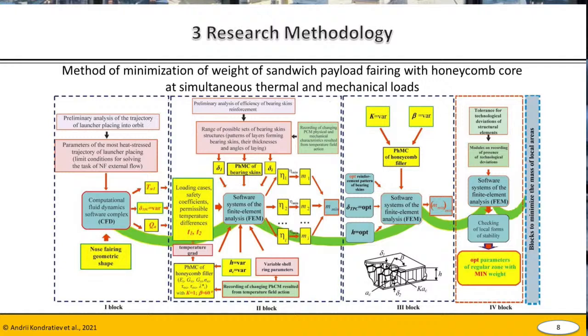The second block allows selecting the optimal thermal protection thickness, height and cell size of the honeycomb filler, and thicknesses of bearing skins. Additionally, this block helps to estimate permissible ranges of temperatures of the inner and outer surfaces of sandwich shells and bearing capacity of the rational variant in all critical areas, taking into account the deteriorations in the physical and mechanical properties of materials due to heating.